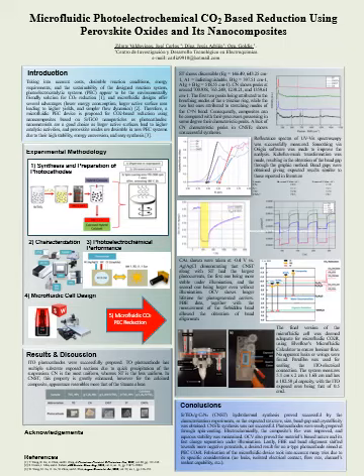first no light irradiation, then irradiated by light in order to observe its photovoltage, and after that the light was turned off in order to observe charge recombination and stability of the photovoltage. In this case, the photovoltage value was negative, which is a great sign, as we were seeking an n-type photocathode, and this shows that charge separation is biased towards a more negative potential, which is desired for reduction processes.